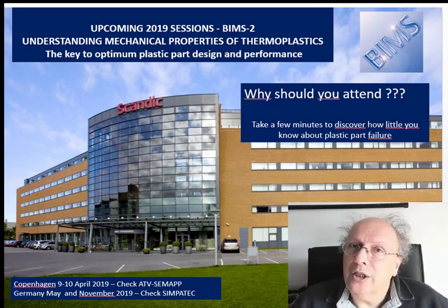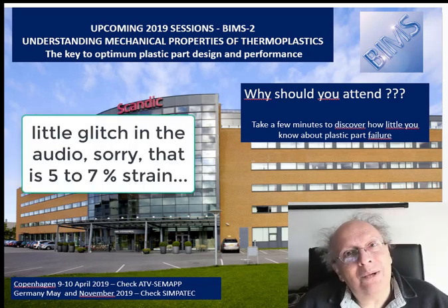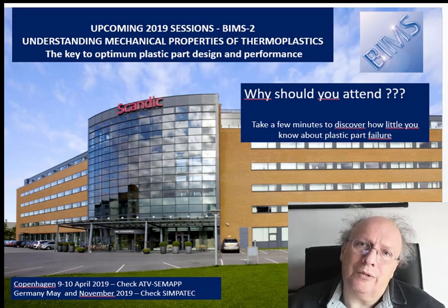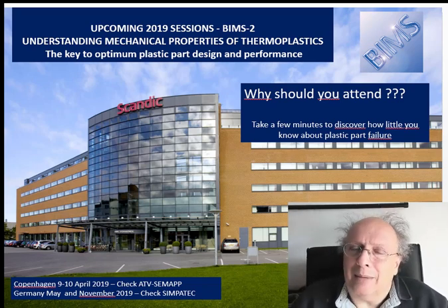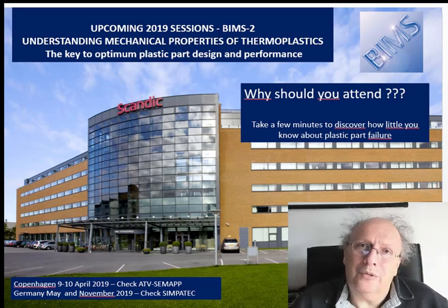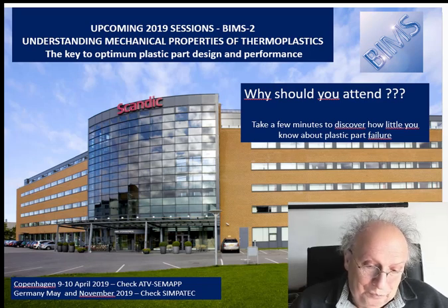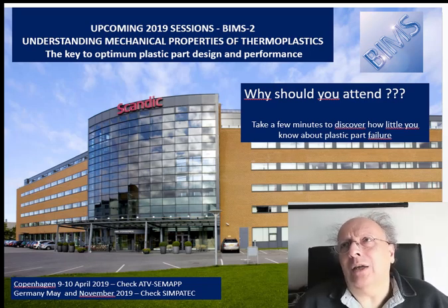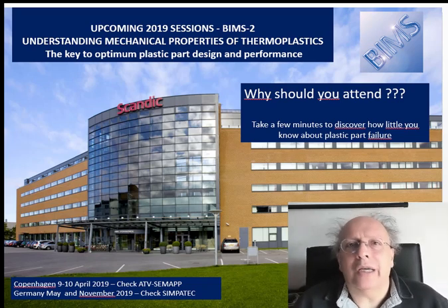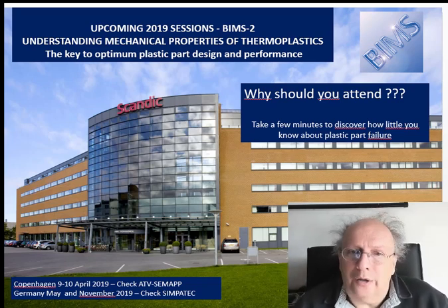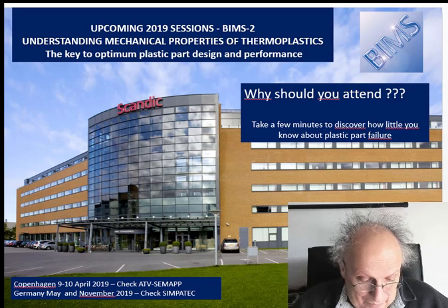Now, plastics are different. They yield at 5, 6, sometimes 7% strain, which is a lot. And there are not so many applications where a strain of 5% is actually acceptable, just from a geometrical point of view, from the functioning standpoint of your application. So in a sense, that's why we tend to consider that yielding in polymer is what you see if you badly overload the part and strain it to 5-6%, which we are not supposed to do most of the time.